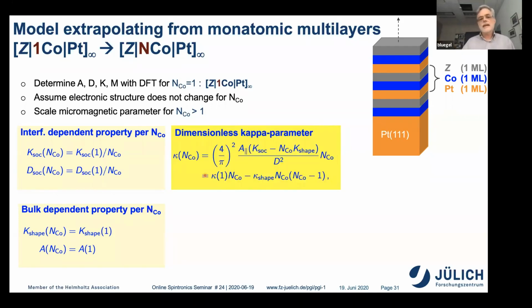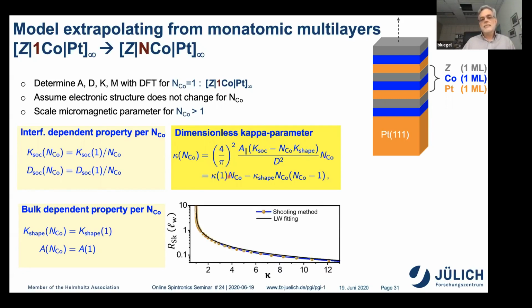And then we can see here how the dimensionless parameter changes now as a function of the cobalt thickness. You see the first term related to this spin stiffness makes your kappa larger and brings this Skyrmion radius down. But the shape anisotropy makes this kappa quadratically smaller and brings you basically to larger Skyrmion radii. So this is a very fine balance where this shape anisotropy varies the kappa and therefore the Skyrmion radius.